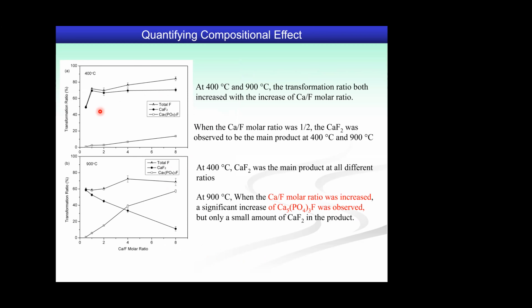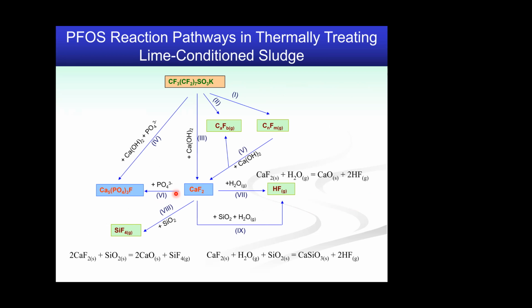So again, finally, you can use a relatively low temperature, say 400 degrees Celsius, if you're looking for sludge drying. Then what you would be relying on is the so-called calcium fluoride mechanism to help you fix the fluorine right there. But very interestingly, if you make your temperature 900 degrees Celsius, and you have the calcium relatively higher, which means high temperature like incineration, and you also add a lot of calcium, there is a chance that eventually your fluorine fixing mechanism will be dominated by calcium fluorapatite (Ca5(PO4)3F). So this gives people a big flexibility of controlling what kind of product they want to end up with and what kind of mechanism they want to trigger to make their product nicely what they expected.